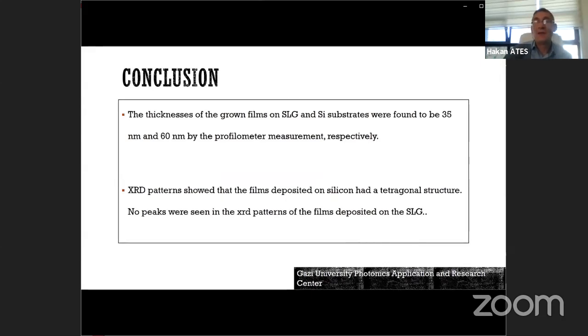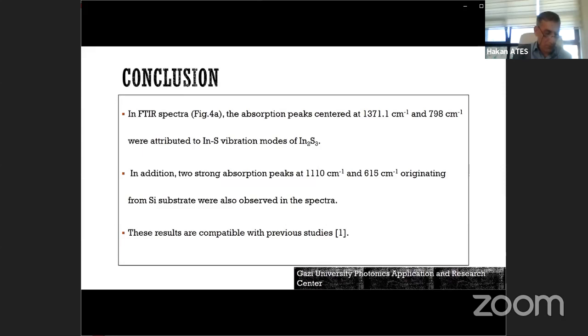Conclusion is the final part. The thickness of the grown films on soda lime glass and silicon substrates were found to be 35 nanometers and 60 nanometers by profilometer measurements, respectively. X-ray patterns show that the film deposited on silicon had a tetragonal structure. No peaks were seen in the X-ray patterns of the film deposited on the soda lime glass. In FTIR spectra, these peaks are fingerprints of the structure, and we determined indium sulfide thin films.